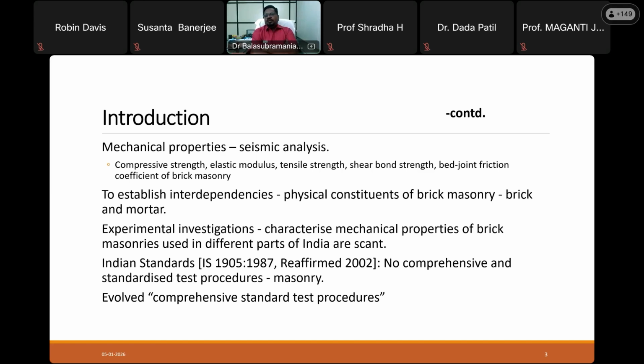See, for India, we have multiple regions with different kinds of brick material and brick availability, depending upon their chemical and mineralogical characters. The strengths vary significantly. So, for instance, if you look at the Indo-Gangetic region, the compressive strengths, even in the table molded ones, will be around 16 to 20 megapascals. When you look at the Deccan Plateau region or peninsular India, it will not be. It will be somewhere around 4 or 5 megapascals. So to achieve higher strengths, people go for compressed molding and improved manufacturing techniques.